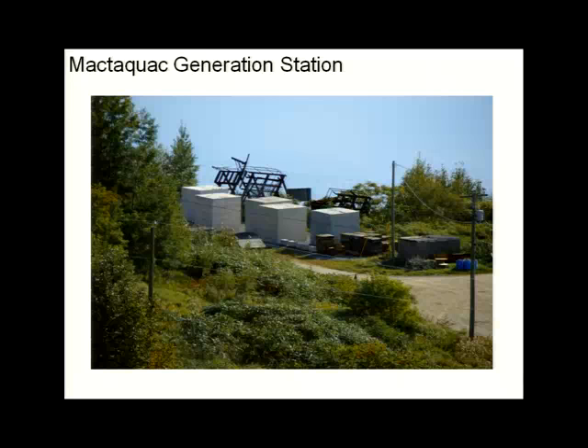Air entrainment is not an effective way to provide enough accommodation for the gel. There's so much gel that's formed. It may provide you a little bit of reduction in expansion, but once those air voids fill up with gel, then they can, one, no longer provide protection for freeze-thaw attack, and you're going to end up getting ASR going on anyway. So they can provide you a little bit of protection, but it's not an effective mitigation means for ASR.